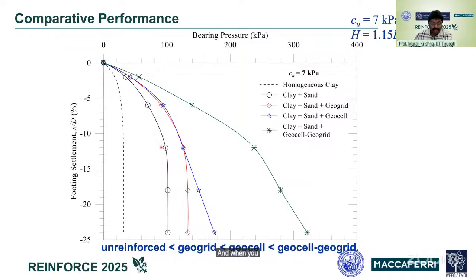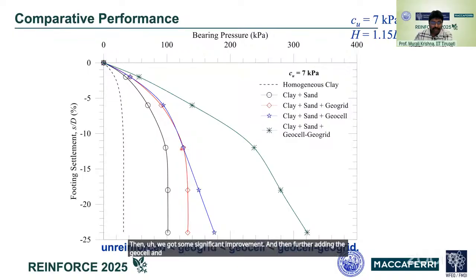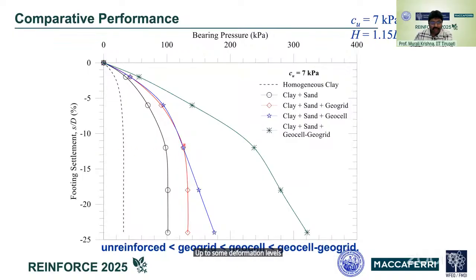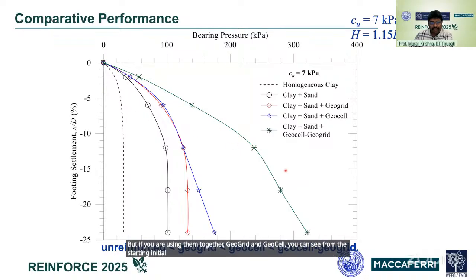And when you provided the sand, some top soil has been replaced with the sand, then we got some significant improvement. And then further adding the geocell and geogrid, how much is the improvement? Up to some deformation levels, geogrid and geocell are almost the same. But if you are using them together, geogrid and geocell, you can see from the starting initial settlement level itself, there is a very significant improvement in the capacity.